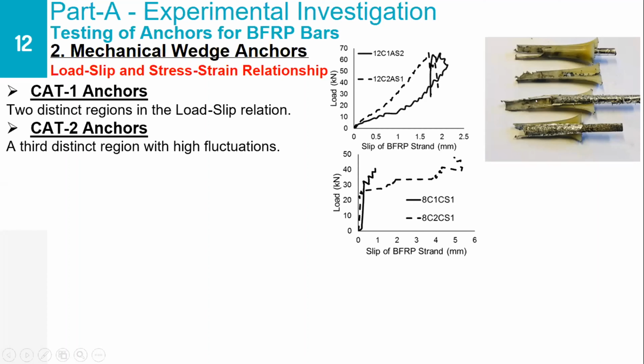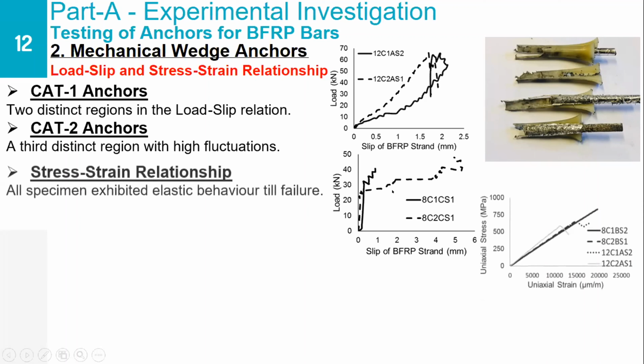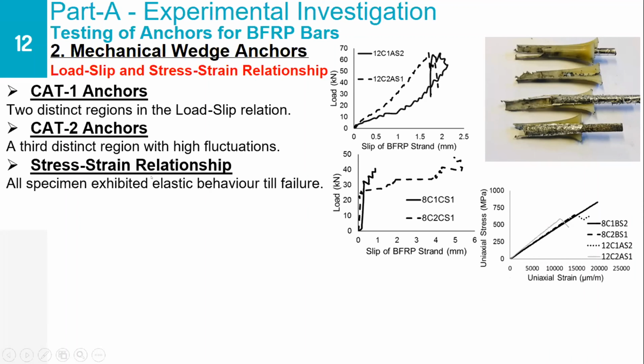So basically these anchors are non-reusable. Once used for prestressing, they undergo plastic deformations and cannot be reused. And because of this, high fluctuations were observed in the load versus slip relationships. Now, as we predicted, the stress-strain relationship of these bars is observed to be elastic. That means they don't have any ductility. So the stress keeps on increasing and they fail all of a sudden without giving any significant warning.